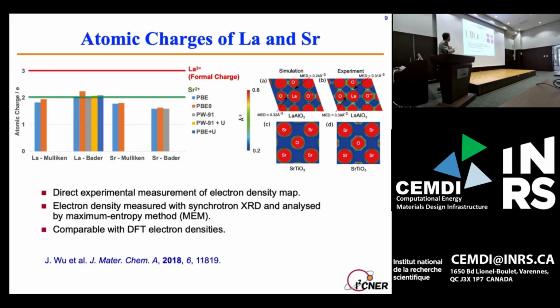And I asked him to calculate me the charge of lanthanum in different oxide materials and calculate me the charge of strontium in different oxide materials. Now, to our surprise, lanthanum came always with a charge of close to +2, far away from +3, which would be the expected charge in those ionic materials. Strontium was coming properly close to +2, just like predicted. So strontium was boring, but lanthanum not at all.